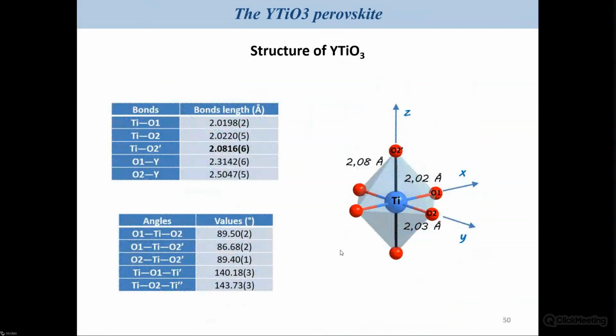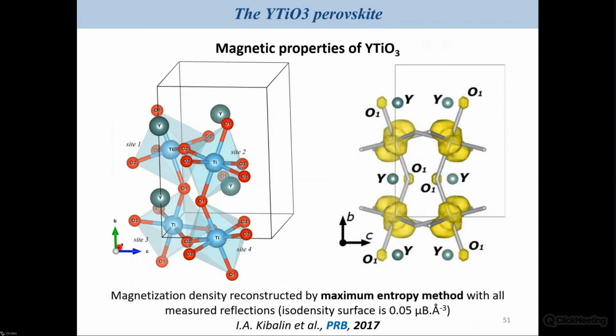This orbital ordering has been studied. I will describe it later, but I will first focus on the specific geometry of the titanium octahedra, for which you have an elongated distance for O2 prime, which corresponds to our z-axis there, compared to the two other equatorial distances. And so, as I told you, you are considering the spin distribution around the titanium atom.